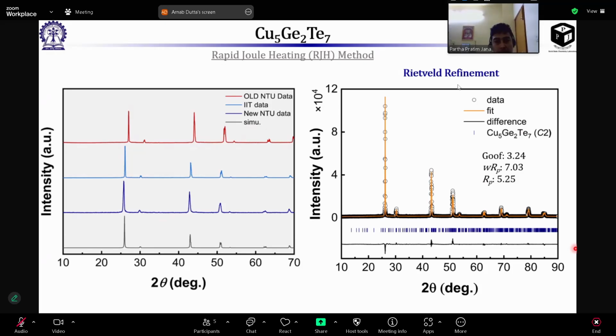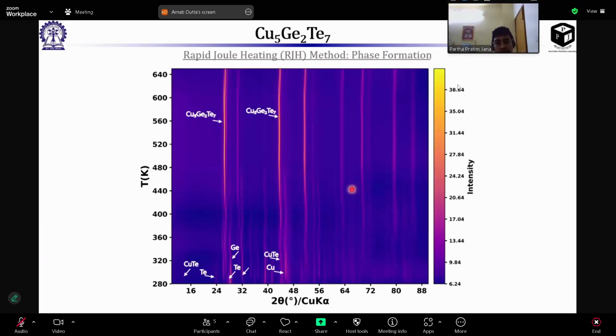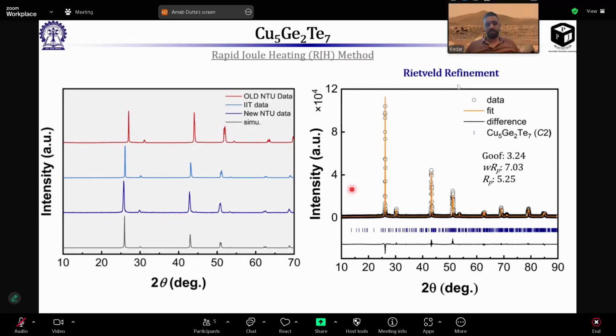Yep. This is a great success of your Joule heating technique. Also it shortened the time period, from days of heating to minutes. After 2 minutes, we have the phase pure sample. And the structure is not distorted, even though it's a very fast cooling. It forms the structure we have seen in our single crystal X-ray data. It's not single crystal, of course, but it's probably a very large grain. It's a really good result.